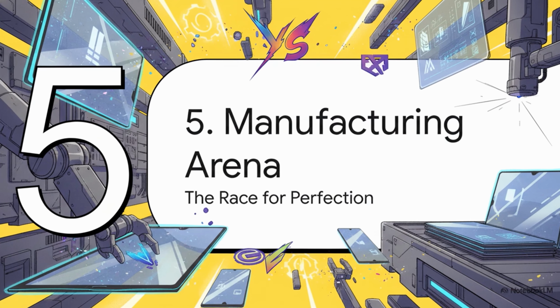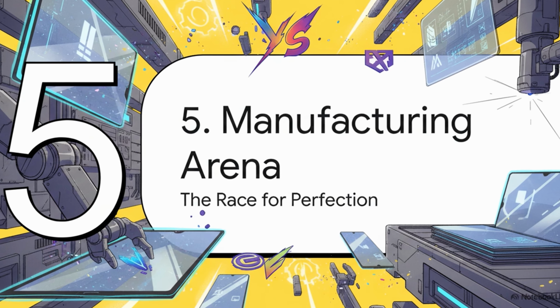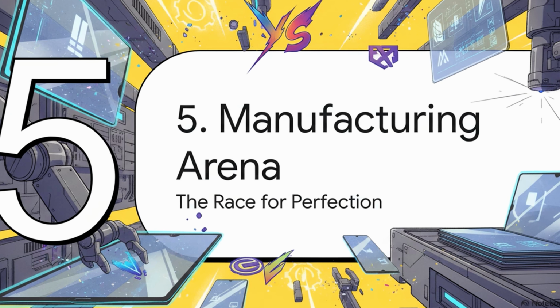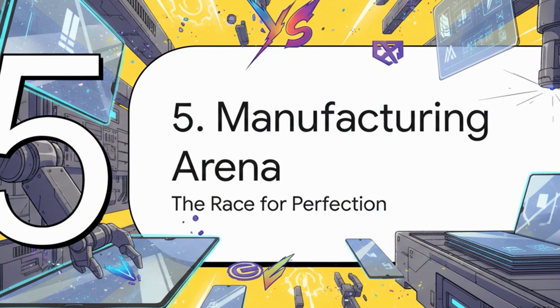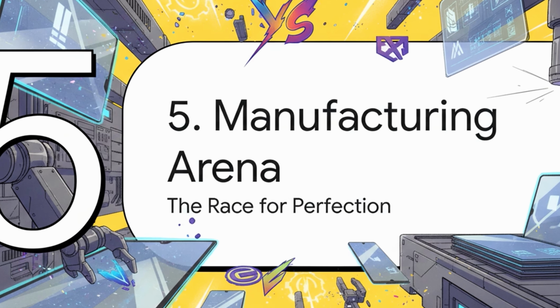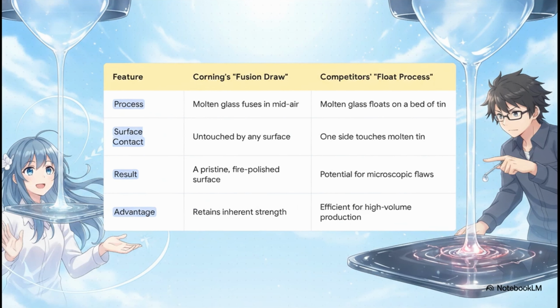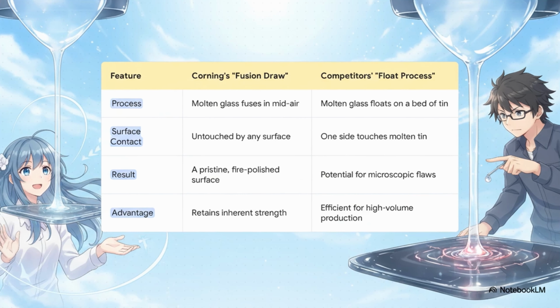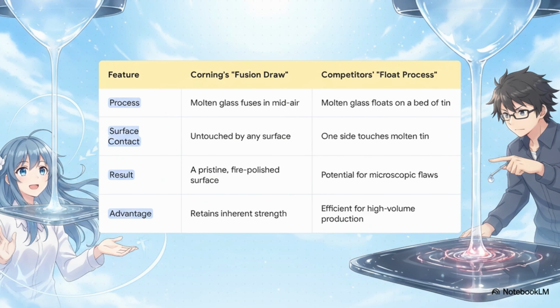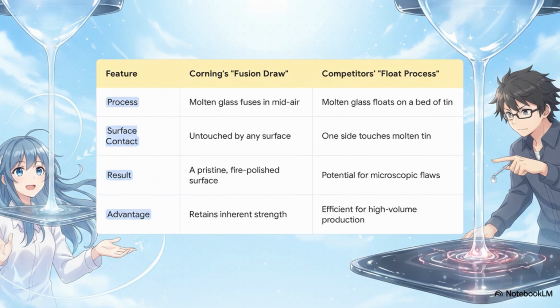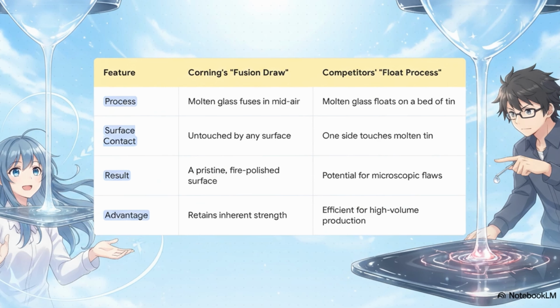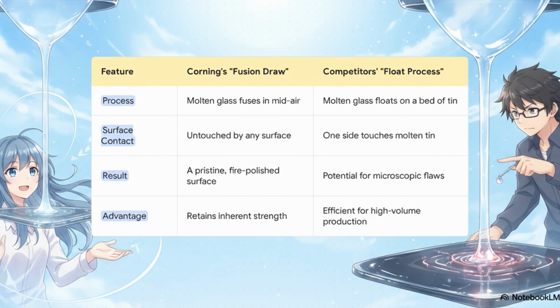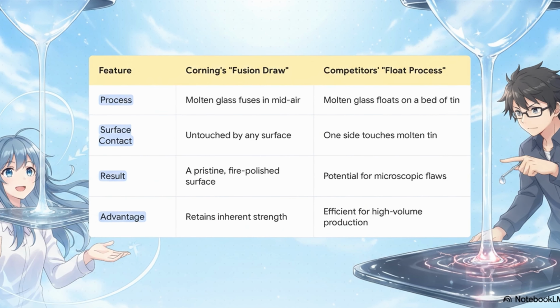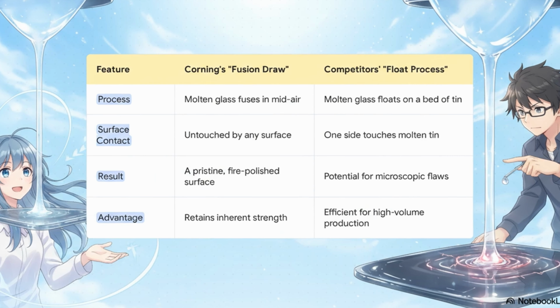But, having an amazing recipe is one thing. You still have to actually make the stuff. And you have to do it flawlessly, which is where the competition really starts to heat up. So you've got two main ways of doing this. On one side, you have Corning with its unique fusion draw process. Molten glass flows into a trough, overflows, and then the two sheets fuse together in mid-air as they're drawn downward. The key is, its surface is never touched by anything.